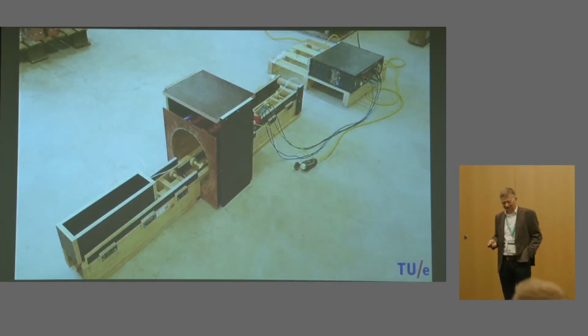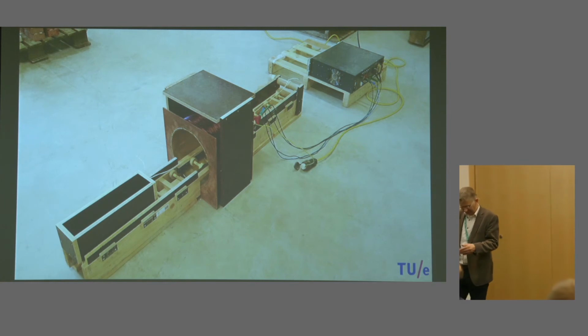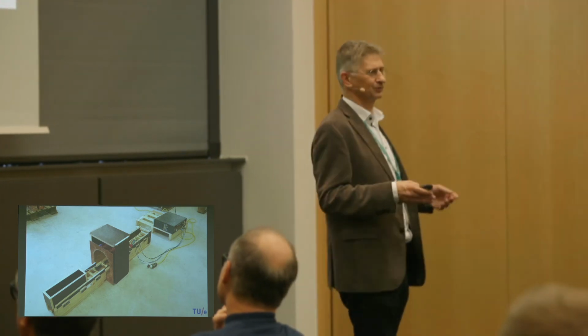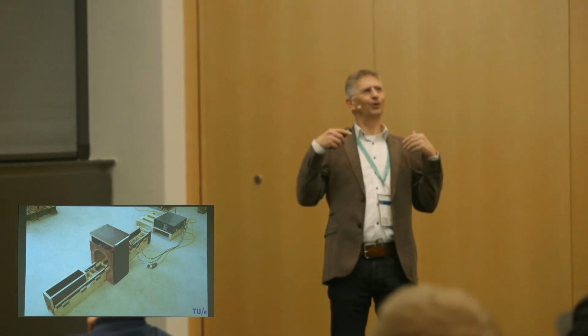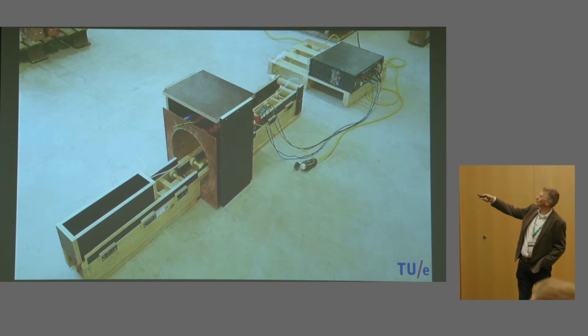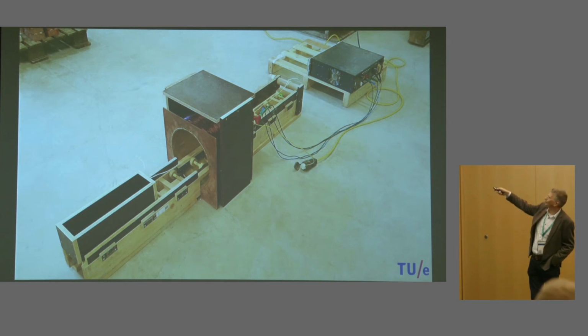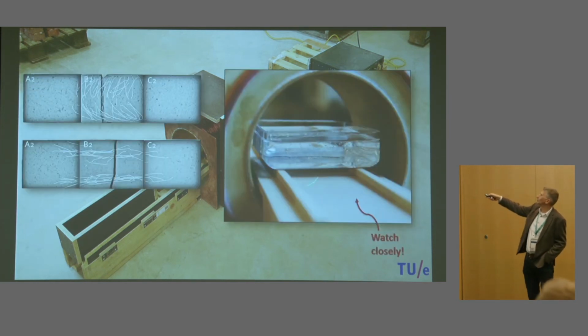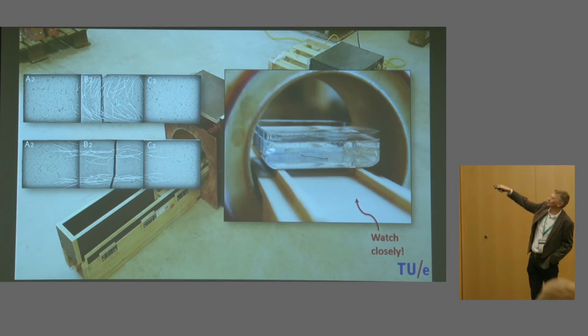Now, there was one student who said, but if you print in this direction and you place a filament and all these fibers come, they will be aligned. And he's correct. These fibers are aligned so far, at least with us. So he tried to see if he could orient them in a certain manner. So he made a magnetic field, so a coil with copper wire, electric feeding on top of that, and then the concrete in here and drag the concrete through. And if you see on this small sample with an oil, so this is the coil, and there is a fiber, and the fiber in the oil is now rotating. Now we did the same trick. We put the fibers in the concrete, pulled them through, and they were orienting the other way around.